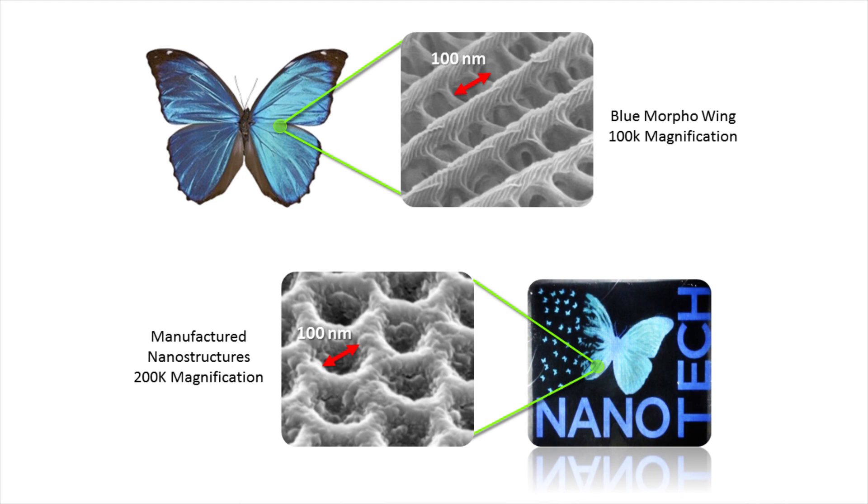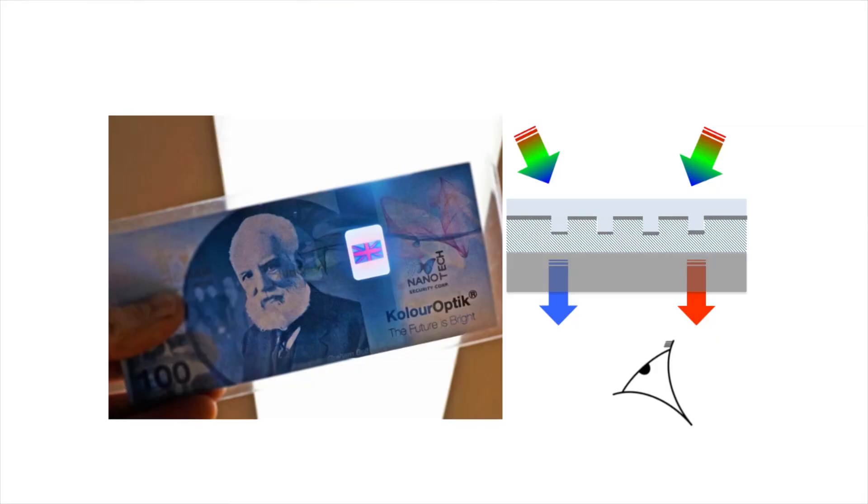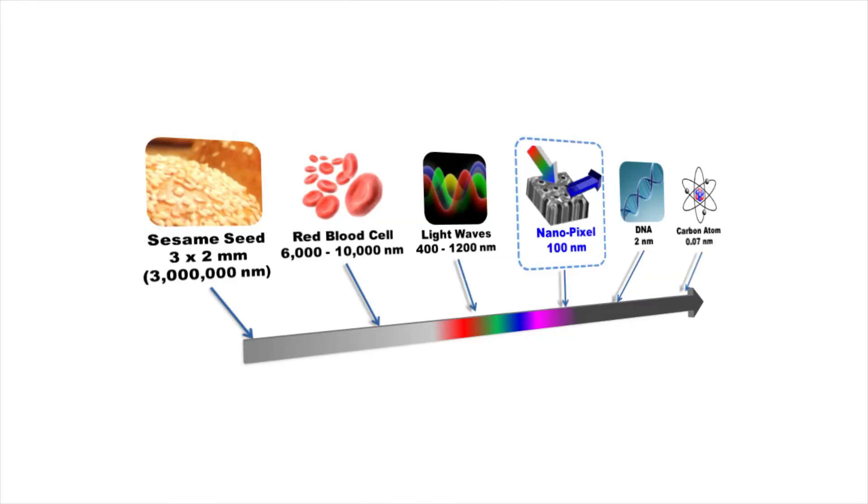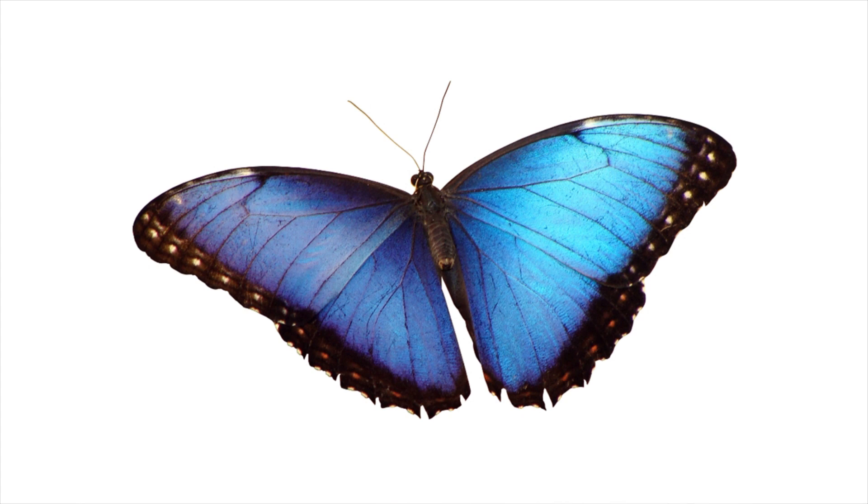So finally, we had that example of how a sub-wavelength, tiny nanostructure can interact with light in a useful way for us to create colors just by using different kinds of structures. We couldn't make the exact same thing because the structures were far too complex to actually build. But we could come close, and after some trial and error working out the size of these structures, the spacing and the geometries, we were able to recreate colors similar to the blue morpho. Eventually, by controlling those parameters, we could actually create just about any color we wanted — engineer nanoscale pixels to create macroscale colors that we can see and put into banknotes, creating one of the most robust security features we have today. It's hard to imagine we would have been nearly as successful without this particular butterfly as a point of reference.